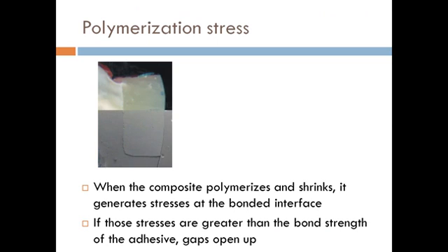So you see here in this example, I'm actually going to go back to show you that this is an in vitro test where we had a premolar and a cavity prep was cut, and then a composite restoration was made. And then you can see that this is enamel margins and this is dentin margins. Then we put the tooth in methylene blue dye, and you can see that there's a lot of infiltration of that dye along the margin, and you see that it's more prevalent close to the dentin than to the enamel.